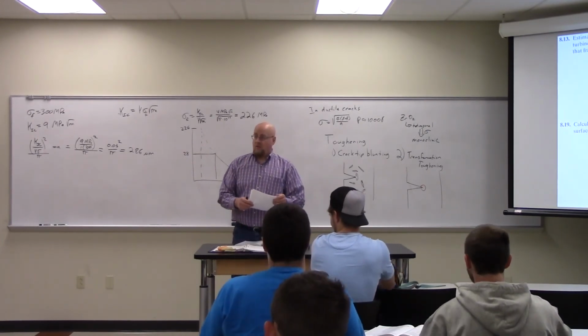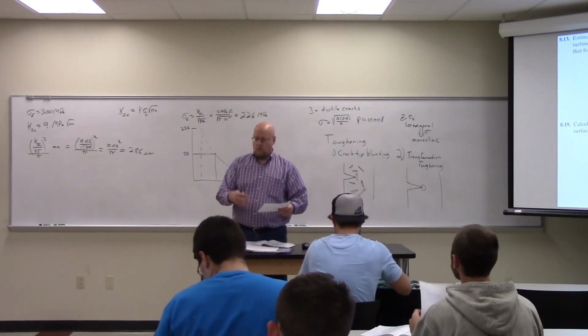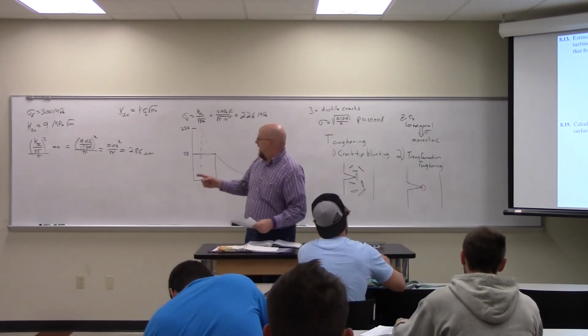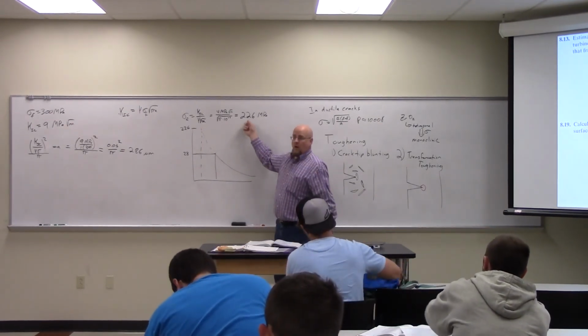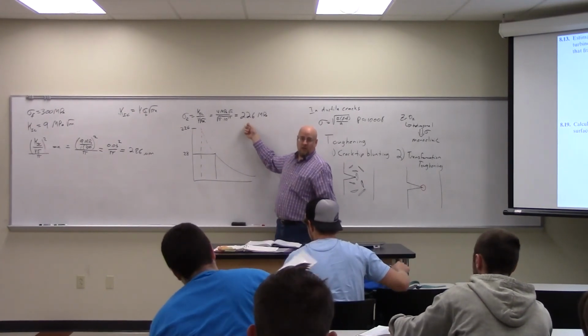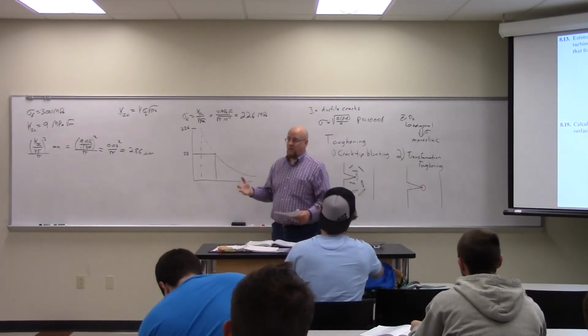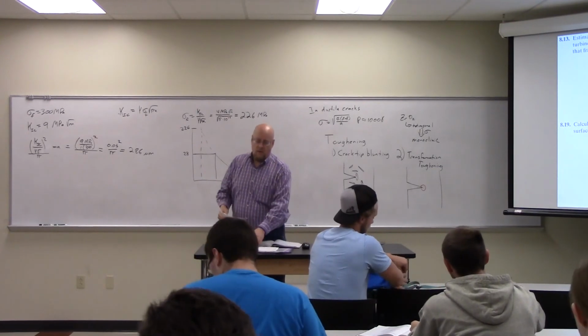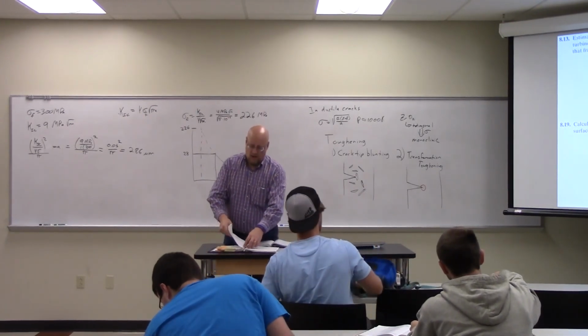If this were glass, I'm guessing, I didn't do the numbers, we would find that this is lower than the tensile strength of glass. And so a 100 micron crack does matter for glass, and you'd have to polish away a 100 micron defect in glass.